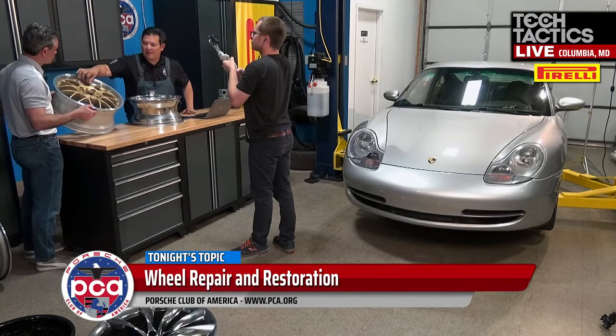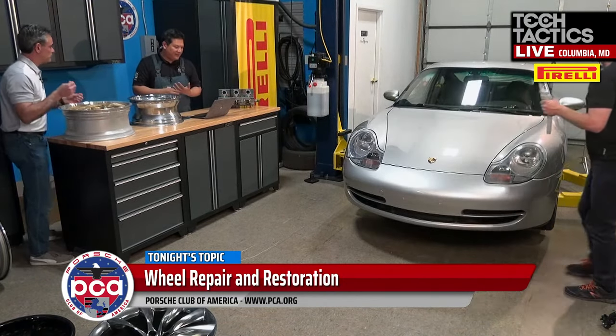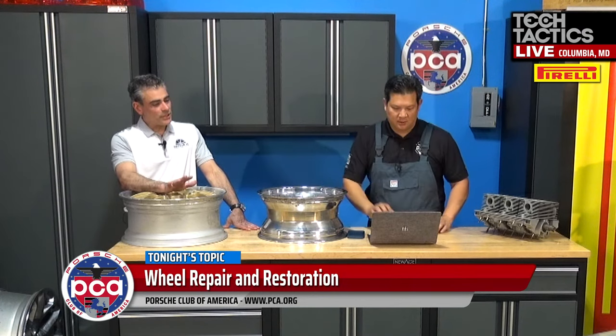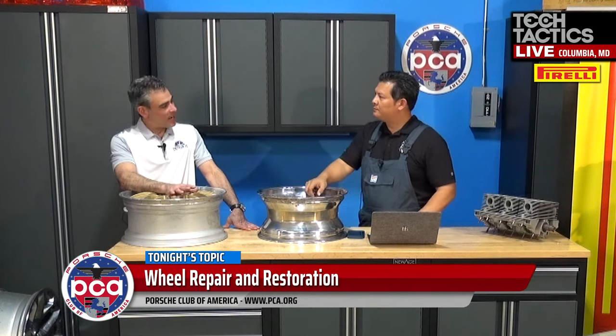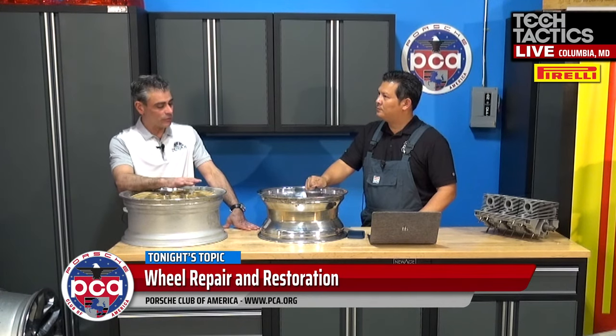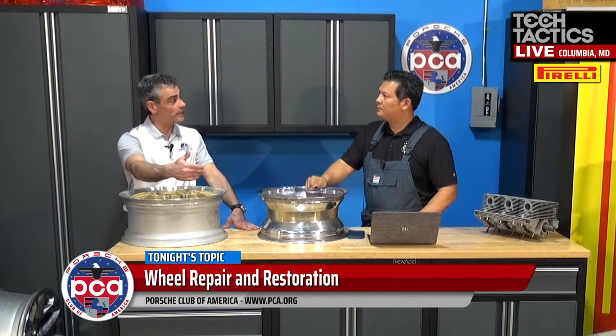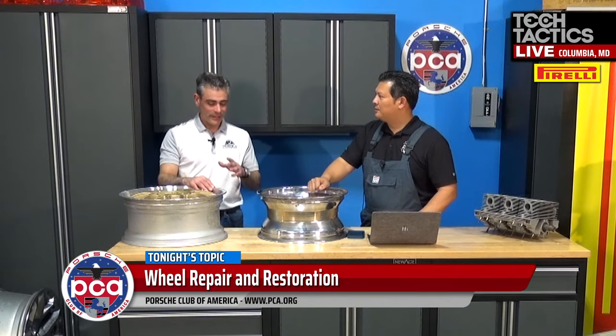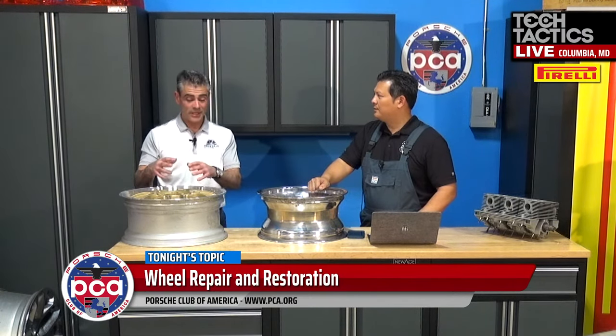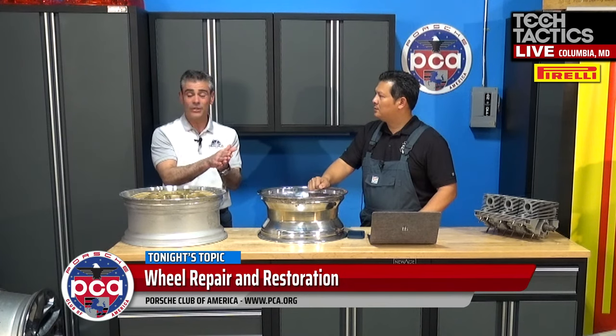Talking about powder coating — we got a question from JD: is it necessary or even advised to clear coat over a freshly polished wheel? The option of clear coating over a polished wheel comes up a lot. From the factory, it's always clear coated — the idea being that if you clear coat over it, you won't need to ever polish it again because it's sealed in. However, it's kind of a double-edged sword. That clear coat will eventually fail on a polished wheel because it's a very slick surface for the powder coat to adhere to long term.